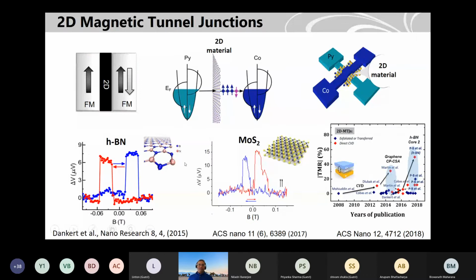And interestingly, this boron nitride tunnel barrier can be used for different applications. For example, here, magnetic tunnel junctions. And here, the two ferromagnets can be separated by just a single layer of boron nitride or molybdenum disulfide. So boron nitride is an insulator, MoS2 is a semiconductor, but still has a gap. But boron nitride should be a good tunnel barrier for spin injection, for the use of magnetic tunnel junctions. It's not only for magnetic, but also superconducting tunnel junctions and other applications. So such things can be used.